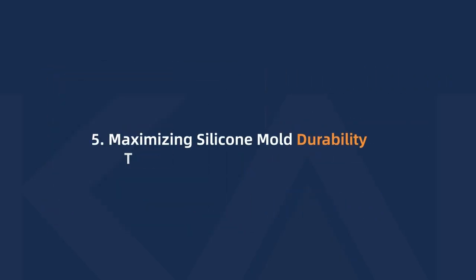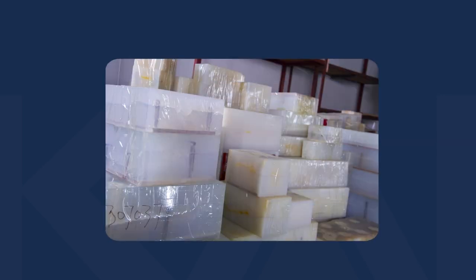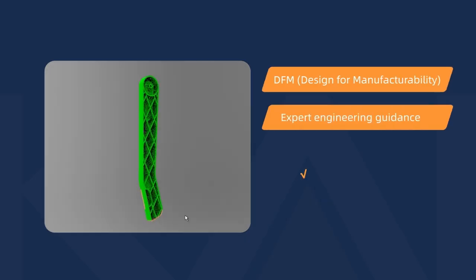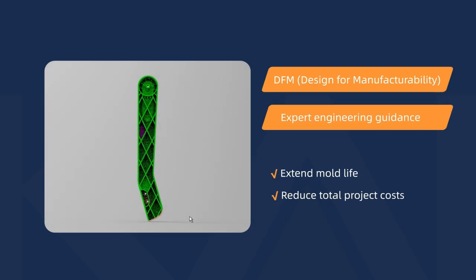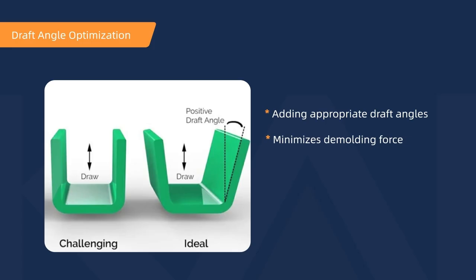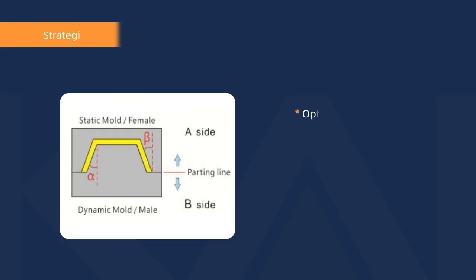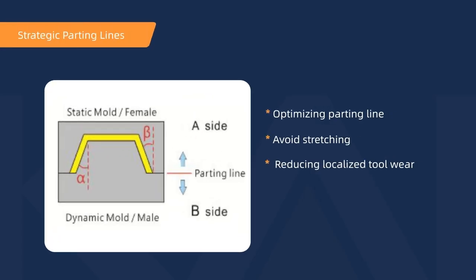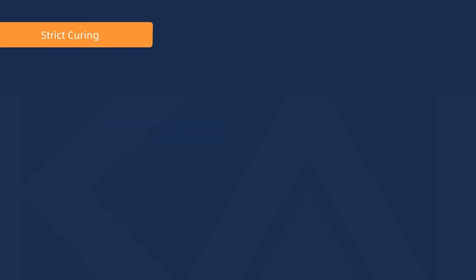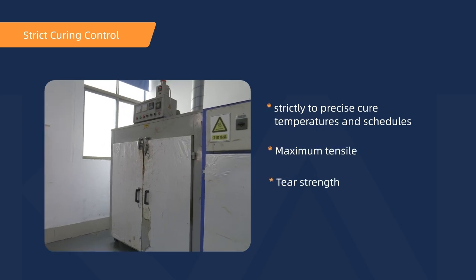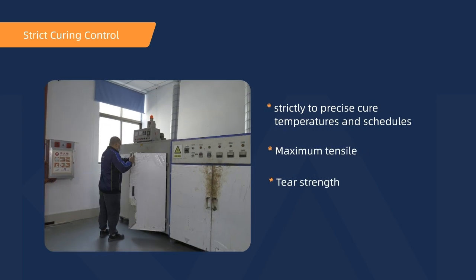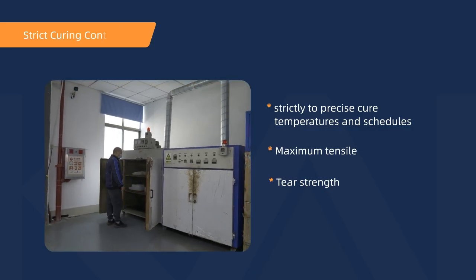Maximizing silicone mold durability through engineering support. Tooling longevity is not entirely unchangeable. Upfront DFM, designed for manufacturability, and expert engineering guidance can substantially extend mold life and reduce total project costs. Draft angle optimization: adding appropriate draft angles minimizes demolding force, preventing silicone tearing around deep features. Strategic parting lines: optimizing parting line placement avoids unnecessary stretch during part extraction, reducing localized tool wear. Strict curing control: adhering strictly to precise cure temperatures and schedules ensures the silicone achieves maximum tensile and tear strength before the first casting cycle.